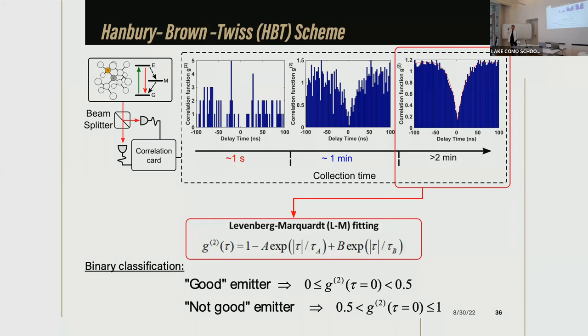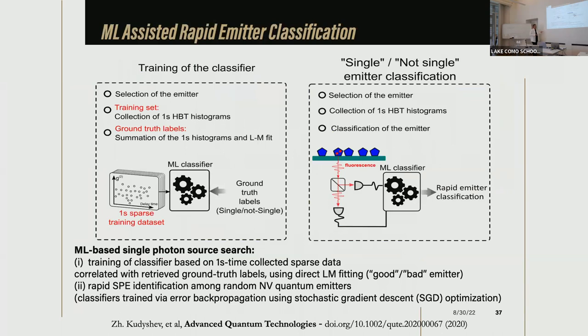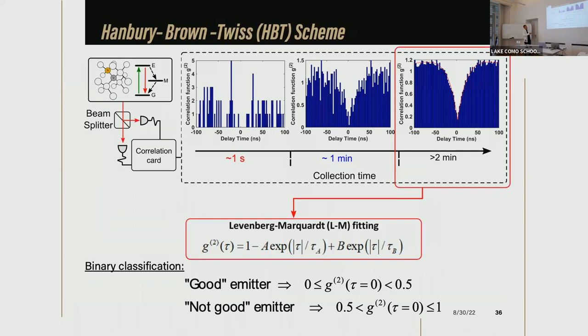But it takes several minutes for one single photon source, and if you work with millions, it's not a scalable approach. If I do only 1 second, the way the spectrum looks, there's no way to fit it with this function. It looks like it's in principle impossible to say. However, that's where machine learning comes into the game. You do conventional neural network training. You first classify your emitters. You know which one is actually a single photon source and which is not, by doing the standard approach. Then you train your neural network. This is a typical classification problem. And after you train it, with very high fidelity or accuracy, the system would say whether it's a single photon source or not, even for this extremely sparse spectrum.